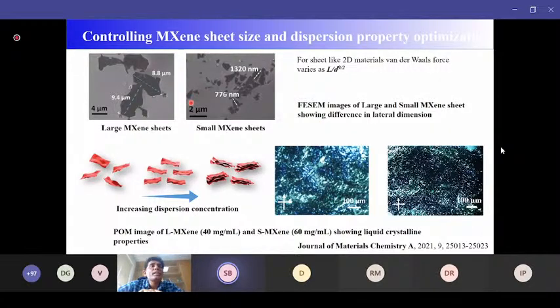So in this case, first we made the larger size of MXene, and this is a smaller size of MXene. We first did two different type of MXene sheets, and then we increased the dispersion concentration up to like 40 milligram per ml or 60 milligram per ml. And in a high concentration, we have checked this with the polarization microscope, and we have found that there is a spontaneous ordering. There are some domains, this kind of bright domains. These bright domains actually signify that those sheets are not random. There are certain domains, there is spontaneous ordering. This spontaneous ordering is known as the liquid crystal ordering.